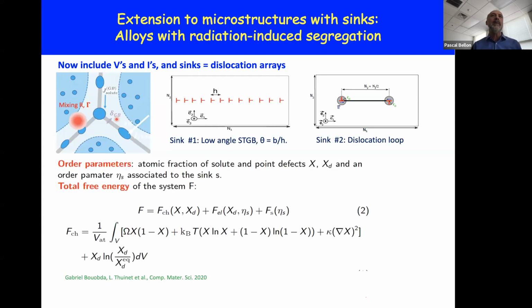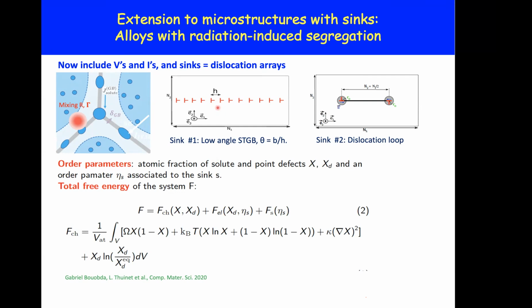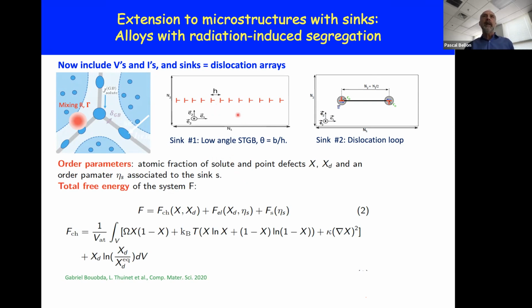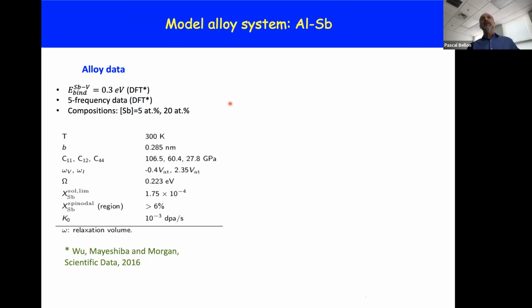So Gabriel Bourda, who obtained his PhD at University of Lille with Ludovic Thuinet, had developed models that can, for instance, represent low angle or symmetric tilt grain boundaries with dislocation cores represented by the elastic field and a phase field parameter that captures and enforces the boundary condition for point defects around this sink. And so we apply this model to an alloy under radiation, that is with this forced mixing.